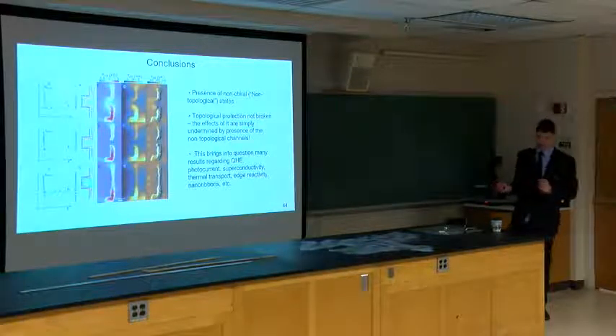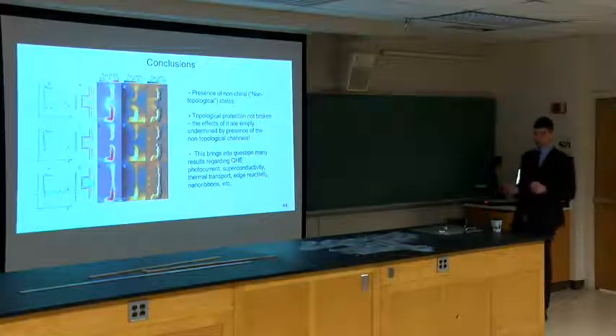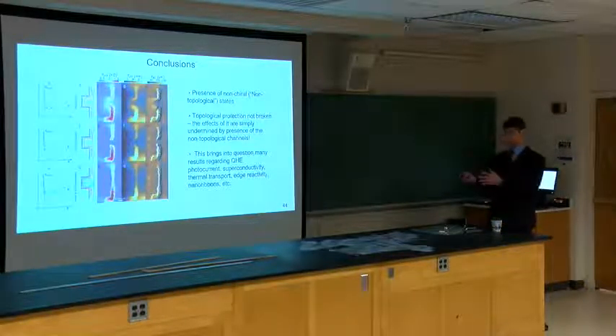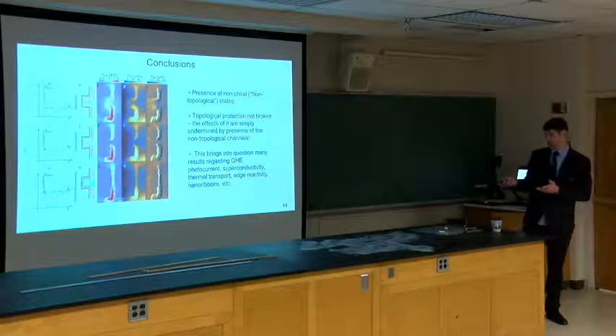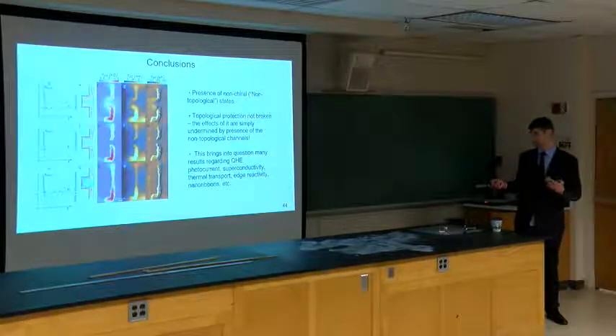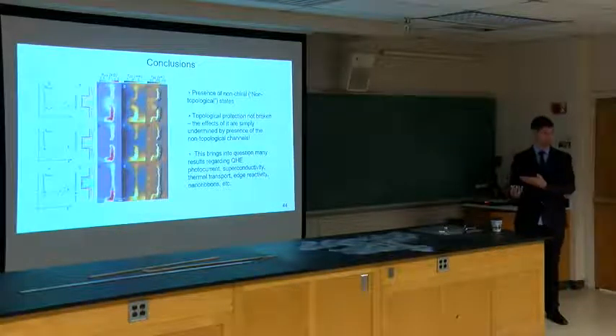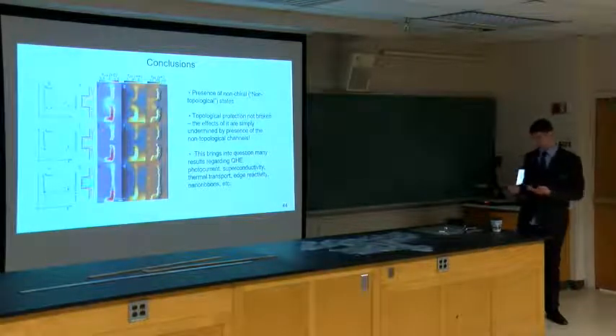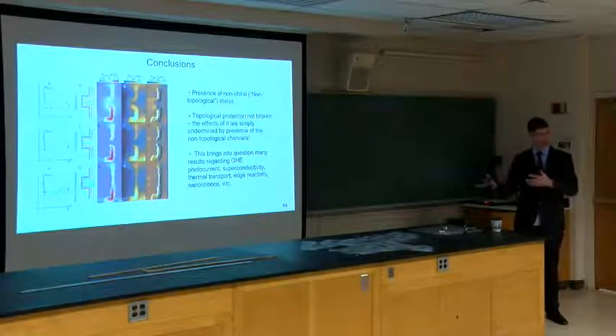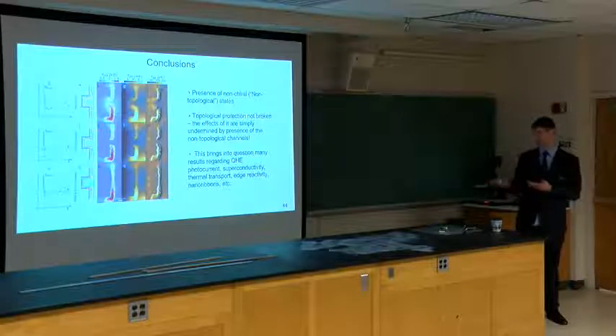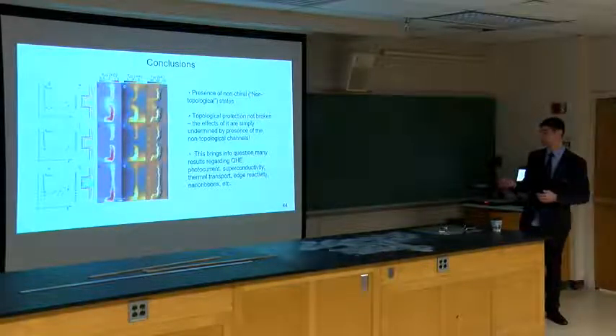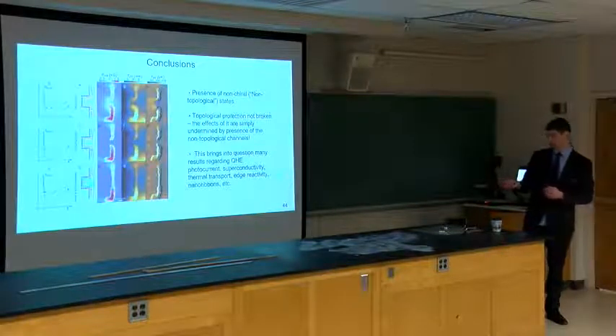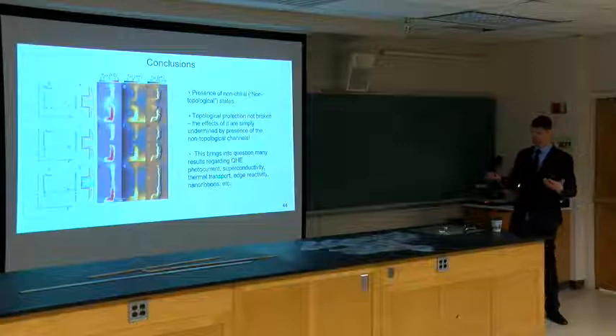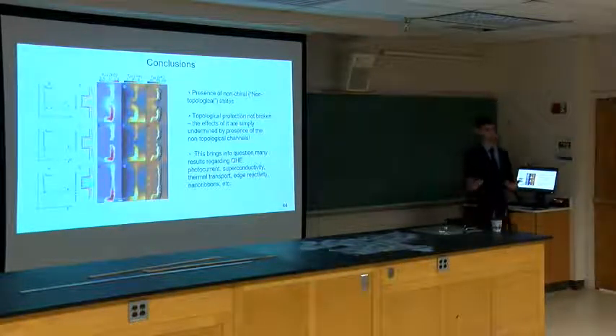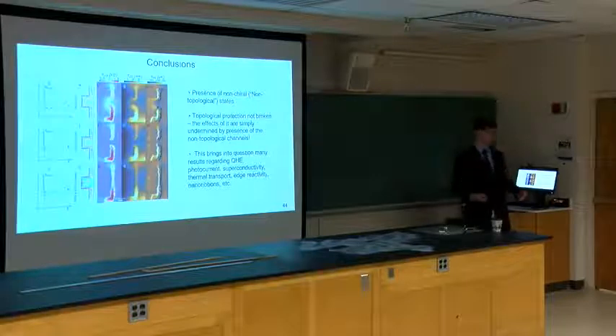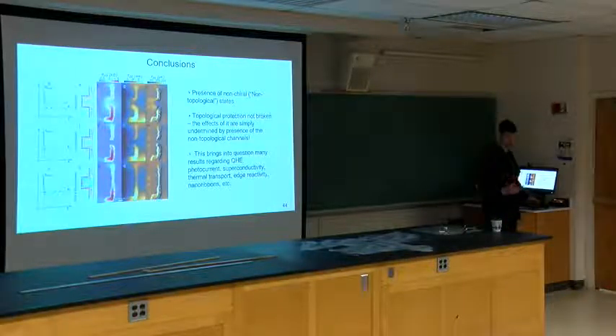And the key factor here, though, is that the presence of this edge doping, which is ubiquitous and would extend far beyond just quantum Hall physics, would deal with anything from photocurrent, edge superconductivity, where I was explaining where the current flows in the previous devices, and actually the edge current that shows up in the quantum point contact that I showed a few data sets ago, very likely is from this effect, and it's really hard to remove, although there are some tricks which I can discuss later. And things like thermal transport, maybe edge reactivity, anybody that makes nanoribbons, the list goes on. If you have an edge field that is not expected to be there, it really can impact, because it could be a PN junction or a PP plus junction.